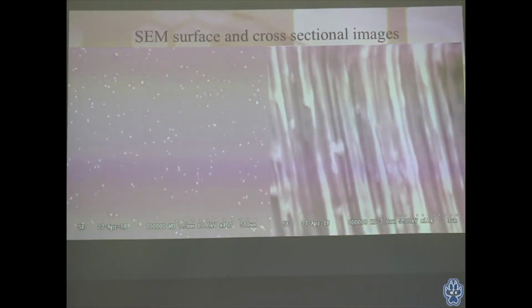So to see if the pores were still really there, or if we had ruined the sample during this process, we cut the sample in half and we took a cross-sectional image, which is this image on the right. As you can see, there's still these vertical channels that are pretty symmetric and spaced apart, which is indicating to us that these tubes created by the nanopores are still residing in the sample. However, when we tried to look to see if there's any nickel inside, it's pretty inconclusive and not very accurate to say that we can see nickel inside these nanopores.